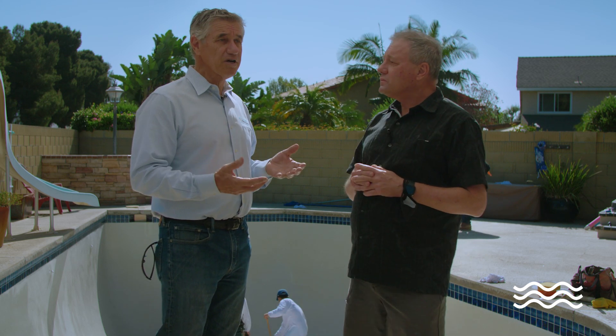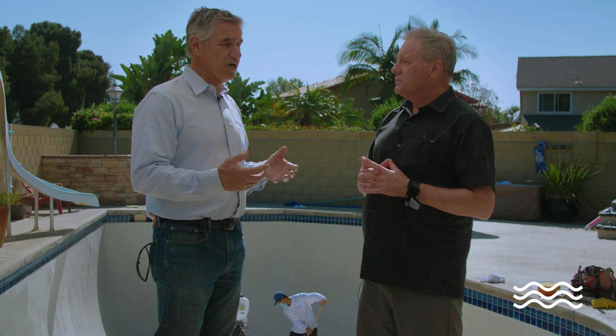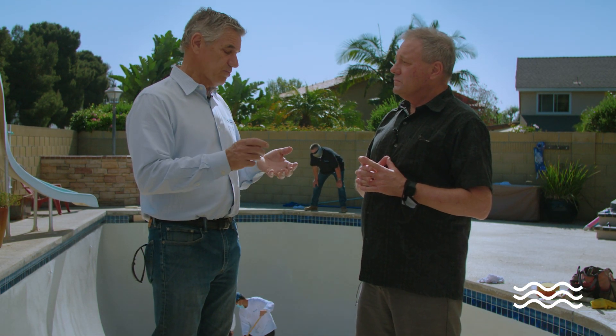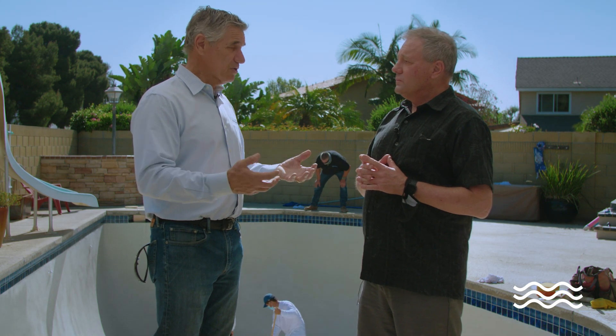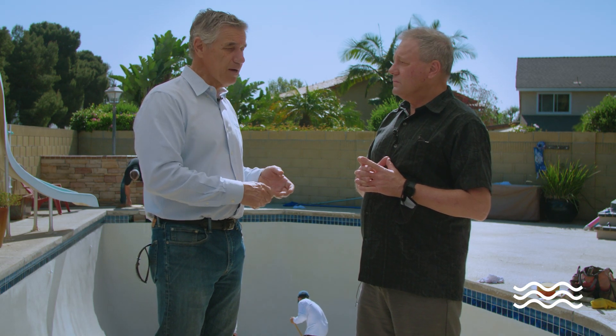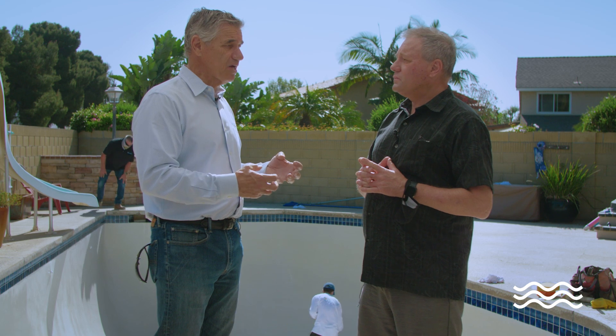I'd like to explain that. When we did our studies at Cal Poly San Luis Obispo years ago, we did almost 10 straight years of protocols trying to find out what we can do with a swimming pool plaster finish inside of the body of water — which has a lot of chemicals and a kind of a nasty environment — to make it last longer, preserve it. What can we do from the material standpoint, application standpoint, water chemistry standpoint? We knew it was a combination: number one, you had to do a really good job of the installation, use top quality materials, use quartzes, pebbles, pozzolan modifiers to help make the cement, fill the voids and capillaries with the pozzolan.